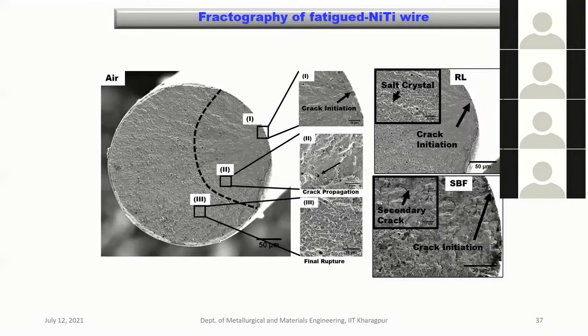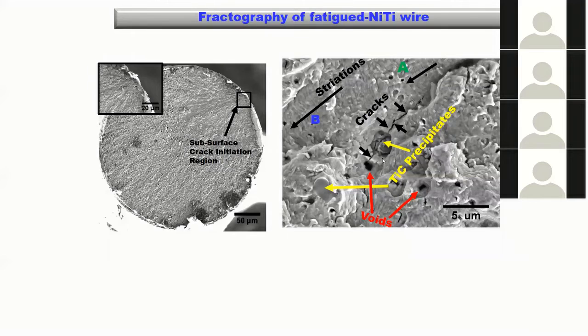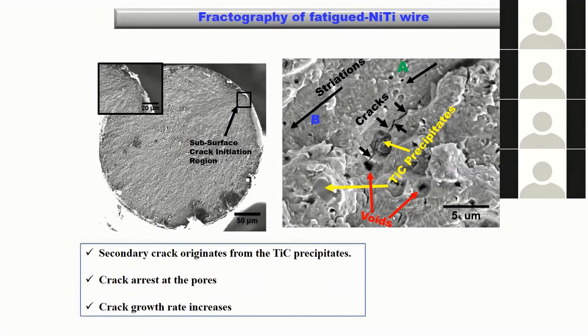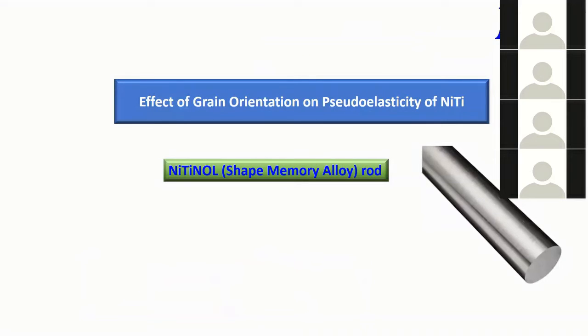From these things, we also have located that wherever these pores are, there were some voids initially of the TiC precipitates, the carbide precipitates, that could also lead to the crack initiation. So the details of this can be found in the publication that I was just showing. So this is one very interesting work, which I thought that you'd like to learn.